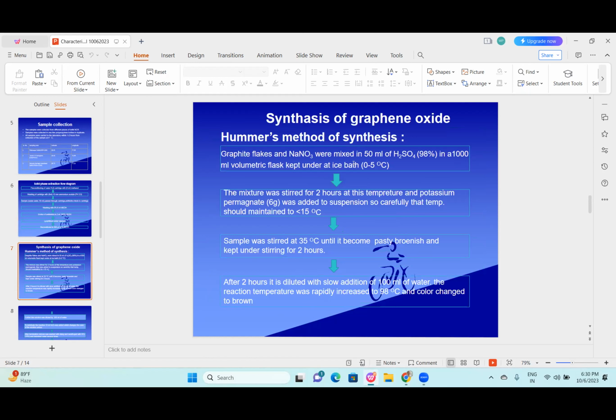Synthesis of graphene oxide. Hummers' method of synthesis. Graphite flakes and NaNO3 were mixed in 50 ml of H2SO4 in a 1 liter volumetric flask kept in an ice bath. The mixture was stirred for 2 hours at this temperature, and potassium permanganate was added to the suspension so carefully that the temperature should be maintained at less than 15 degrees centigrade. The sample was stirred at 35 degrees centigrade until it became pasty, brownish, and kept under stirring for 2 hours.